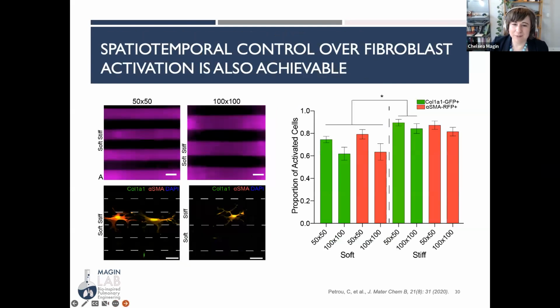The really cool part about this system is that our secondary polymerization reaction is controlled by light. So that means we have control over this reaction in space and in time. So I just wanted to show an example of that. These materials here, we incorporated a fluorophore into the secondary reaction so you can visualize it. These are 50 micron by 50 micron stripes. And you can see this purple stripe here is a stiff area, and this dark stripe here is a soft area.